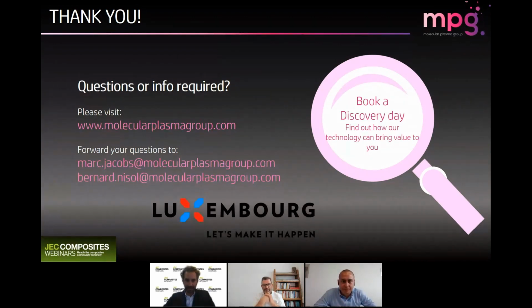Okay, we have a few minutes left to take as many questions as possible. The next question is from David Tondero. Is there a risk of polymer intrinsic properties modification, like intrinsic viscosity or crystallinity? Bernard, yours again. I wouldn't expect that. I don't know exactly what we're talking about, if there's more specificity to that question, but no. And that's exactly how we also differ from corona. We won't induce much damage to the surface of the polymer. We won't exceed temperatures such as 40, 50 degrees Celsius. So in most cases, we don't reach a Tg of the polymer, so we don't induce changes in the mechanical or other intrinsic properties of the polymers. And by the way, in most cases, we don't even change the surface topography of the polymers, and we've seen that so many times.